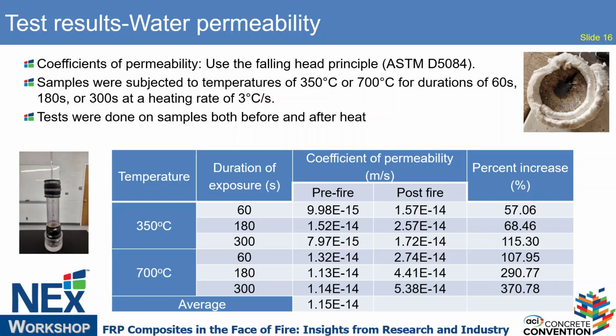350 degrees C, and we also exposed some samples to 700 degrees C, and 700 degrees C is almost the peak temperature we measured over the slab surface during the vehicle fire test. We exposed those samples for 60 seconds, 180 seconds, and 300 seconds at a heating rate of 3 degrees C per second, which is the heating rate we measured during our vehicle fire test.